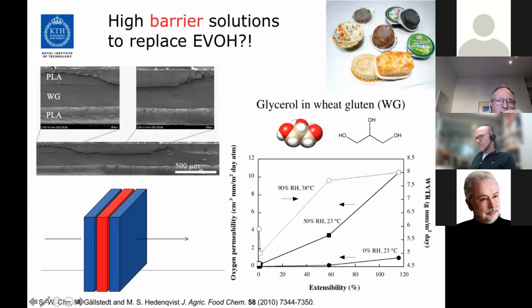I mentioned that proteins are good gas barriers. This is an example where the aim is to replace EVOH, which is expensive and fossil-based. So if you put the wheat gluten as a middle layer and you protect it from moisture by having PLA on each side, you can actually get quite good oxygen barrier properties.